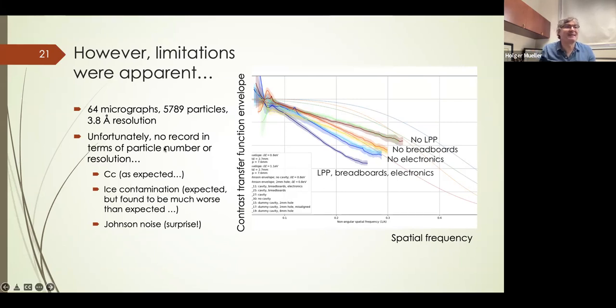Well, the first is chromatic aberration, as expected, because the relay optics that we're using causes a little bit of extra chromatic aberration, and that is going to affect the resolution. Second, also expected, was ice contamination, and our Titan microscope is slightly worse than a state-of-the-art Krios. But unfortunately, what we found is it's not just slightly worse, it was much worse. And the third was a complete surprise to us, it's Johnson noise.